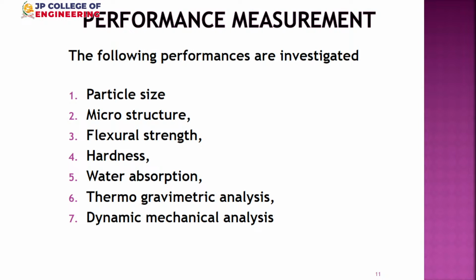Then the final one shown is dynamic mechanical analysis. This is for testing a viscoelastic material, where the stress and strain will not match together. In a metallic material, the moment you apply stress, immediate strain will set in. But in the case of a viscoelastic material like a polymer, there will be a lag between the strain onset and the application of stress. This lag gives a provision for your damping capacity. So by using dynamic mechanical analysis, we are going to evaluate the damping behavior of the material. These last 3 tests are very important from our application point of view.